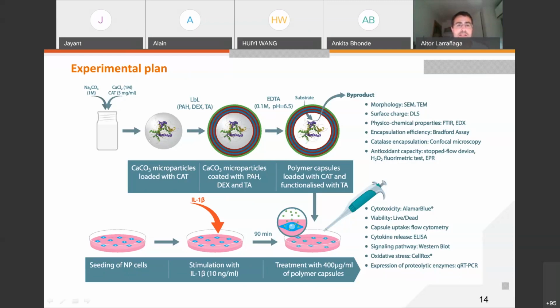Then after the fabrication of the sacrificial template, we proceed with the layer-by-layer approach by simply incubating alternately these particles with positively and negatively charged polyelectrolytes. And we finally functionalize these polymer capsules with an external layer of tannic acid. Then we remove the sacrificial template with a calcium chelating agent, EDTA, in very mild conditions that allow us to preserve the integrity of the encapsulated enzyme. In parallel, we isolated primary nucleus pulposus cells from bovine tails, and we stimulated them with the pro-inflammatory cytokine interleukin-1 beta. And finally, we test the therapeutic potential of our capsules in this inflammatory model.